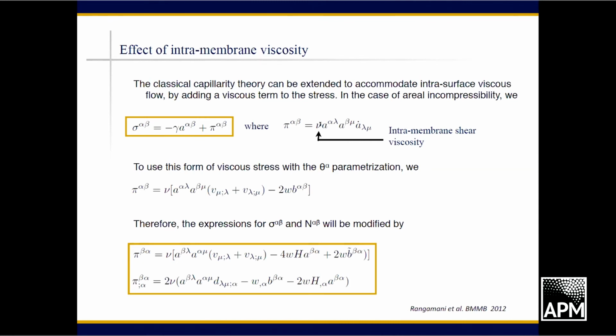We only have a shear viscosity as a linear function of the straining in the surface, which is essentially the Lie derivative of the evolving metric in the surface. And that Lie derivative is simply the material derivative of the evolving metric. To compute it, we simply take a conventional time derivative in the convected coordinate description of the kinematics. That Lie derivative turns out to be related to the symmetric part of the tangential velocity gradient in the surface, and to the normal velocity coupled to the curvature.